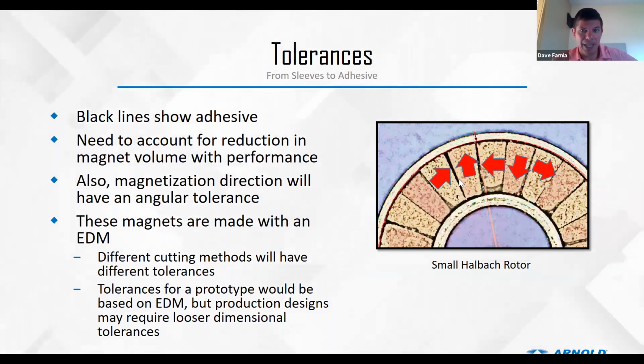At the same time, magnetization direction, very tiny Halbach array magnets. Each of these magnets is going to have a little bit of an angular tolerance. So it's not quite perpendicular. It could be up to a couple degrees off in that direction. And so is that going to have a significant impact on the end result is something that we would try to look at in the design phase.